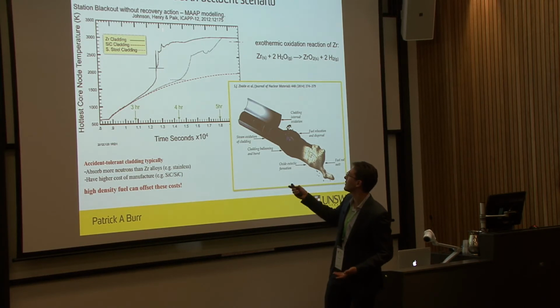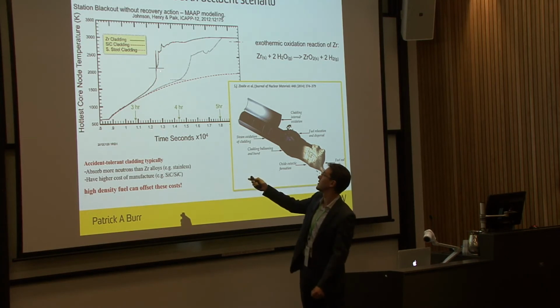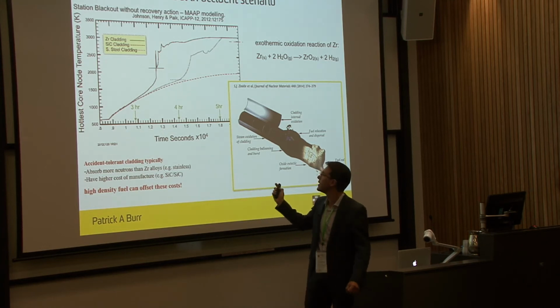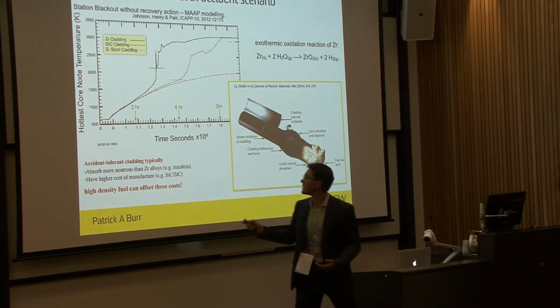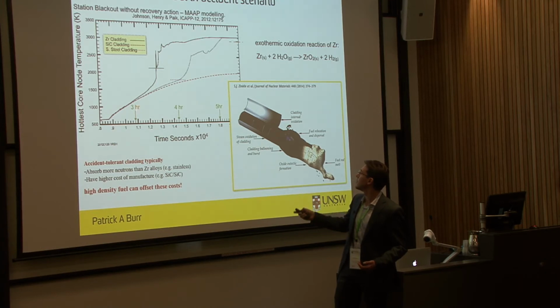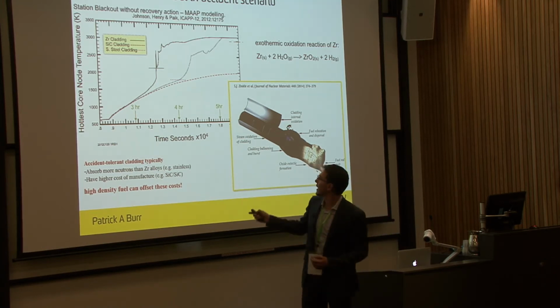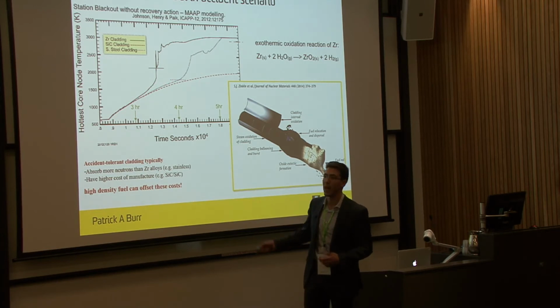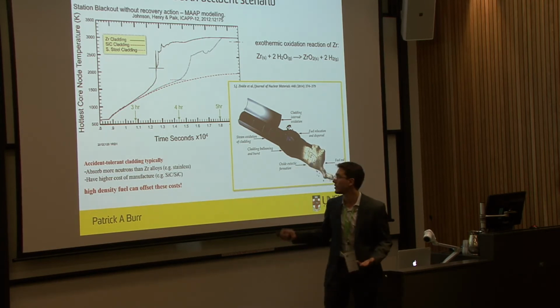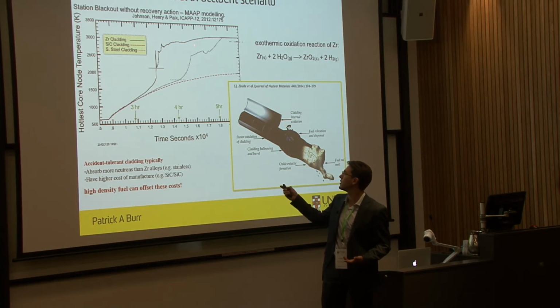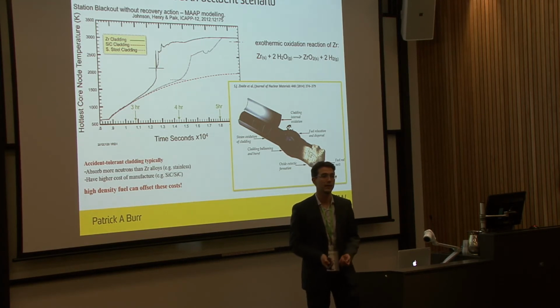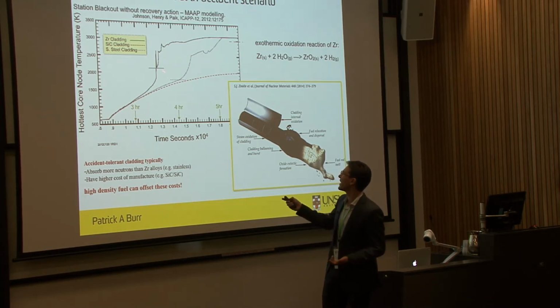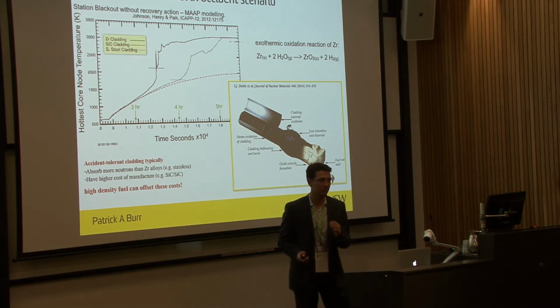And so you get to this runaway reaction, which happens at about 3.5 hours in a conventional PWR reactor, and that melts your fuel, which is indicated with that solid black line. So if you instead move on to, say, stainless steel, which is this purple dotted line, you can see that the reaction kinetics are a lot slower for oxidation, and you produce less energy in the oxidation reaction. So you actually gain quite some time before the runaway reaction. But the melting temperature of stainless steel is actually much lower. So you actually only get about half an hour. Half an hour is not little.